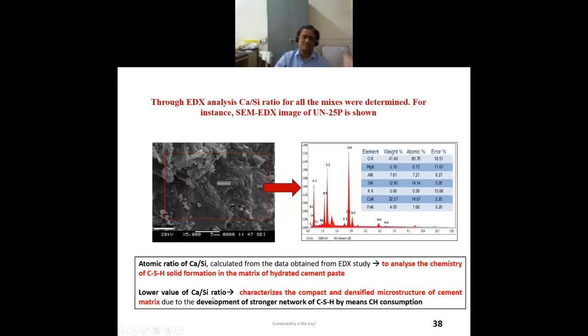So a lower value of Ca/Si ratio, remember, characterizes the compact and densified microstructure of the cement matrix, due to the development of a stronger network of C-S-H by means of CH consumption. The moment CH is consumed, it reacts with the additional silica and forms calcium silicate hydrate. Remember, the more CH is consumed, the lesser your Ca value is going to be. So the Ca/Si ratio is going to be less, and that signifies a compact and dense microstructure.